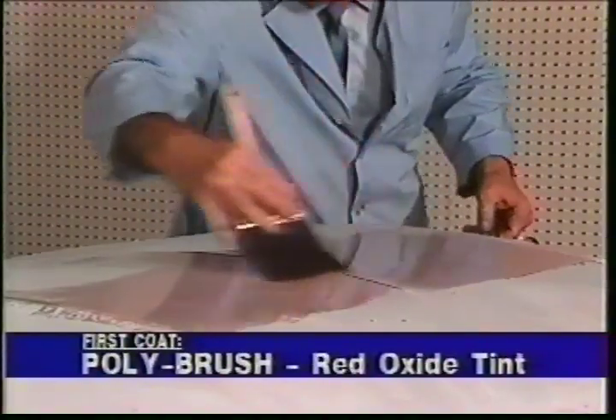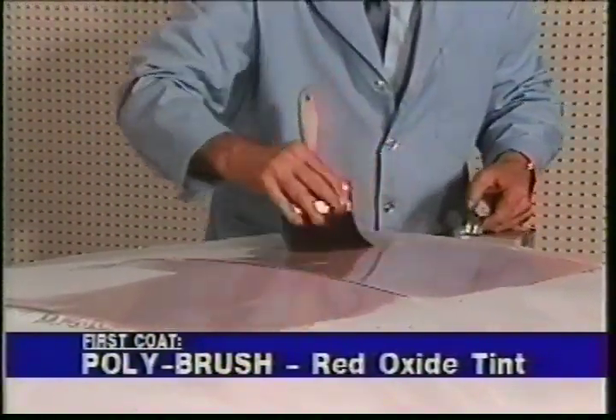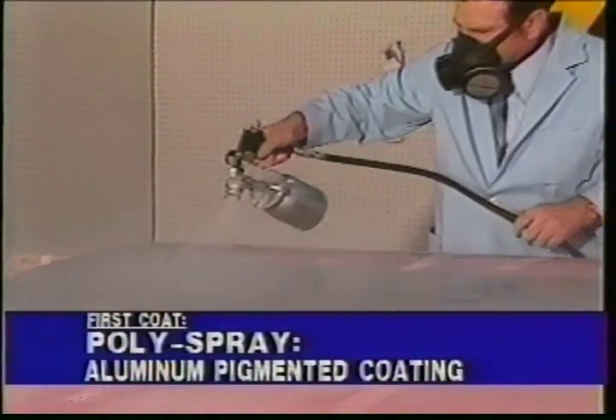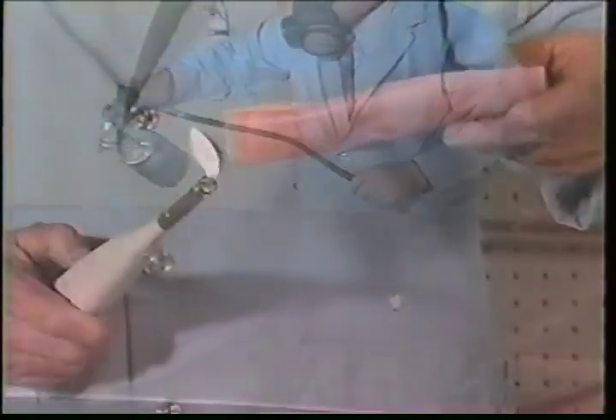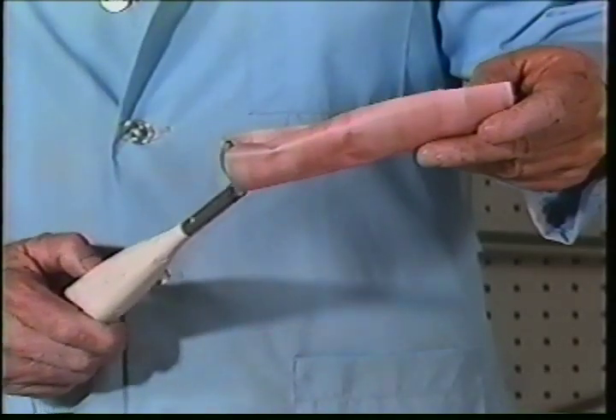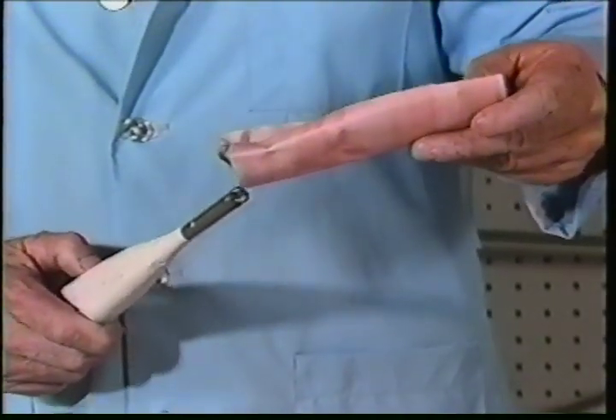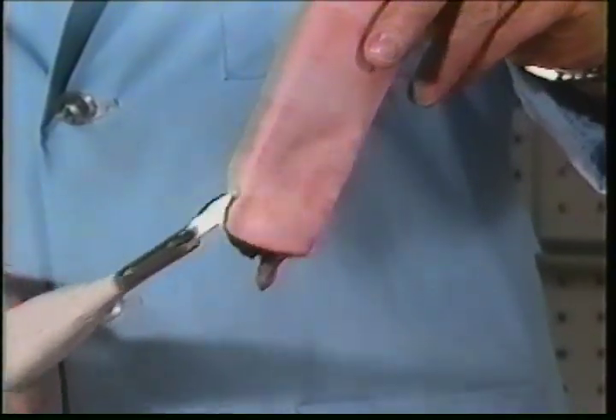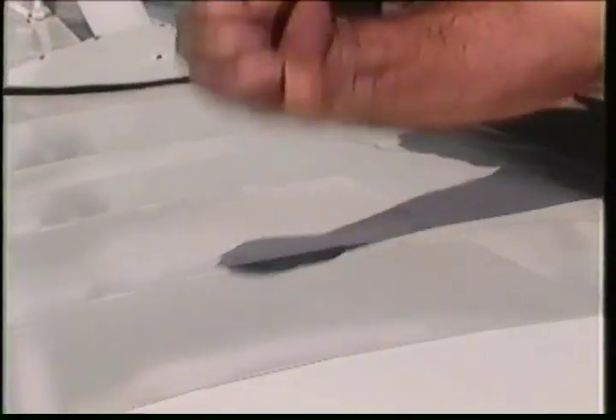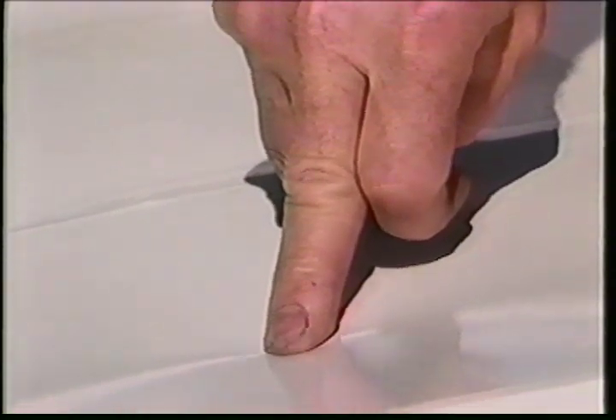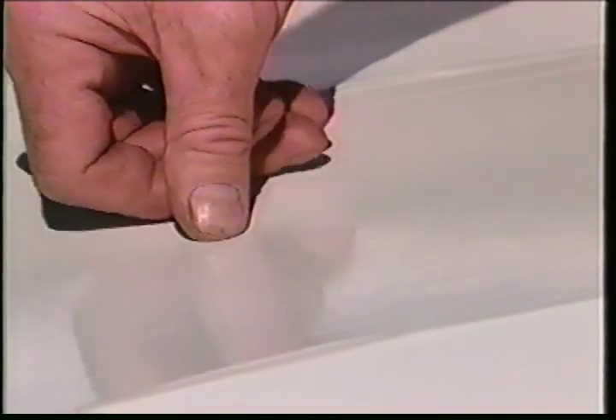All Polyfiber fabric is identified with a stamp at 3-foot intervals. Remember, the first coat, Polybrush, has a red oxide tint and is also available untinted. Polyspray is an aluminum pigmented coating. When a fabric sample is available, a burn test also sets the Polyfiber coatings apart from cellulose and acrylic-based polyurethane coatings. Firm thumb pressure on a fabric panel which leaves a temporary depression is an easy test that distinguishes the Polyfiber coatings from all other types of solvent-borne coatings. If it ringworms or peels off, it isn't Polyfiber coatings.